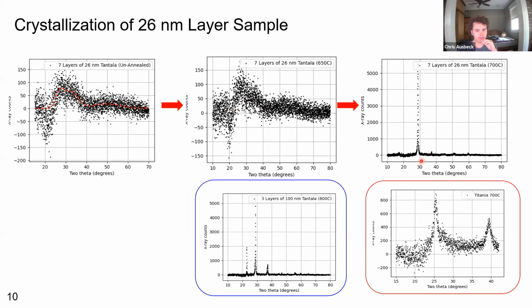And you can see here that there's this 29-degree peak, which is very similar to this tantala peak we see here in the tantala silica samples. We also see a much smaller 36-degree peak as well.